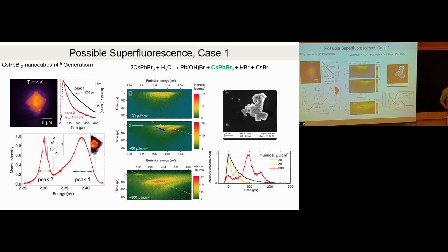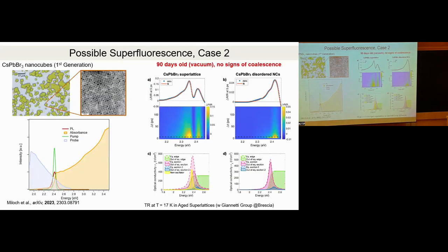The second case: we reverted back to the nanocubes made by the first generation synthesis, I think the most similar to the ones originally reported in 2018. In this case, we actually saw, at low temperature, the appearance of an additional resonance. So I believe we reproduced the observation from the 2018 paper. This sample had to be kept in vacuum for essentially 3 months. But these particles did not show any signs of coalescence into bulk material. So some coarsening happened, perhaps bringing cubes together in some local domains, which then resulted in the appearance of this new resonance.